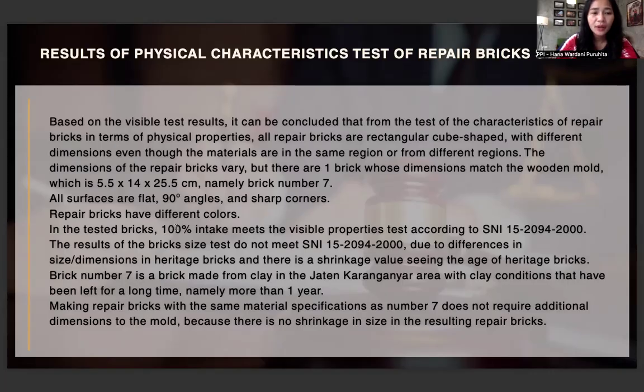In the test brick, 100% intact meets the visible properties test according to SNI 15 in Indonesia, Standard National Indonesia. And the result of the brick size test don't meet SNI due to difference in size or dimension in heritage bricks, and there is a shrinkage value seeing the age of heritage bricks.